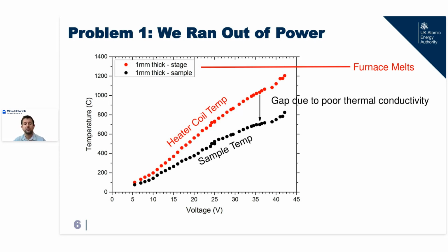This was a millimeter thick sample, which is pretty thin as samples go. But even at relatively modest temperatures of 500-600 degrees, you've got a 200-300 degree gap between what you're plugging into your heater and what eventually reaches the top of your sample. Now, this wouldn't be a problem, except that when you want to hit those 800, 900 degree temperatures, your furnace starts to melt before your sample gets to those degrees. Your tantalum heater wires have an upper limit of about 1300 degrees. And so this really does limit you in how hot you can get your sample. Can you actually get enough power in without melting your heater system?